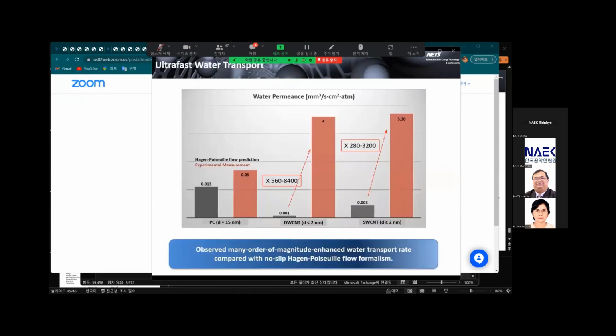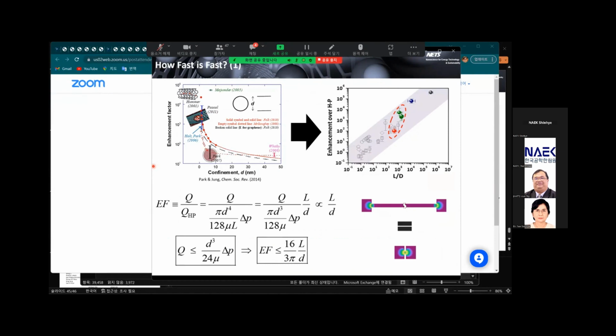Obtained water permeation rate was orders of magnitude enhanced in comparison to the Hagen-Poiseuille flow prediction. The slip flow theory could explain this result, which I believe is true, but this theory itself may not explain why the enhancement is only hundreds or thousands instead of a million or larger than that. This question is related to the conundrum of our field.